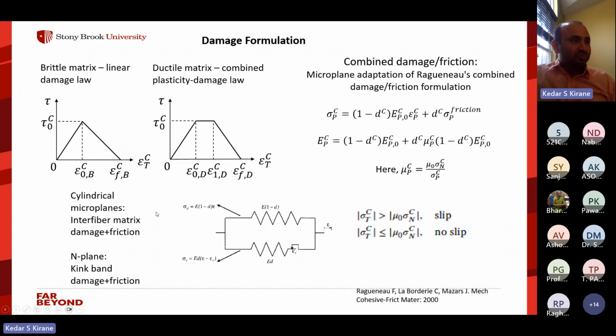We actually have two versions of the model possible. One is if the matrix behavior is brittle, we can capture it using a simple linear softening law, which again has to be driven by shear, because locally the failure is being caused by shear. Now, if the matrix behavior is ductile, we can have a trapezoidal damage law where there is some kind of plateau and then softening. So you can see that this damage law is actually very, very simple. There is nothing complicated about it. It is just damage driven by local shear. And of course, these parameters, these damage initiation thresholds, completion thresholds, we have to calibrate using test data. So it's either this linear softening or ductile, like trapezoidal damage.